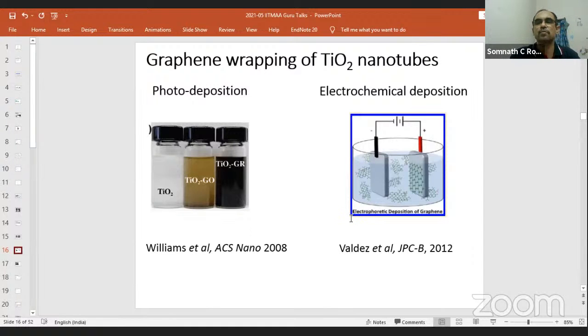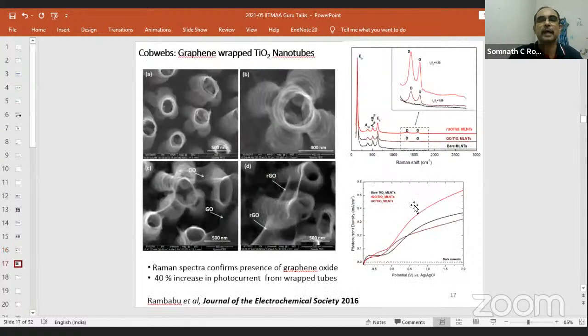The other approach that we took was, we again took those TiO2 nanotubes grown on titanium foil, and we used this as an electrode again. And then we put this graphene oxide here as an electrolyte. And again, we did electrochemical deposition. What happened was that the layers of graphene oxide covered and wrapped around the nanotubes so beautifully, as you can see here. I'm sure you can all see. Of course, there is not much contrast here, but as you can see, we got a beautiful structure as if someone has gift wrapped our TiO2 nanotube.